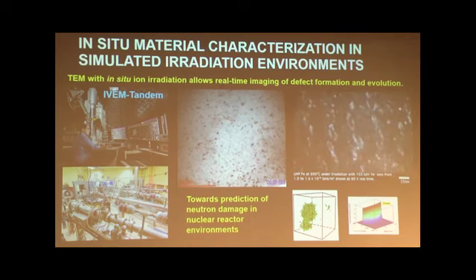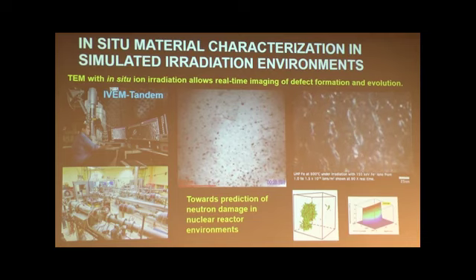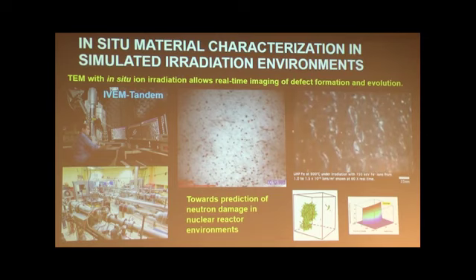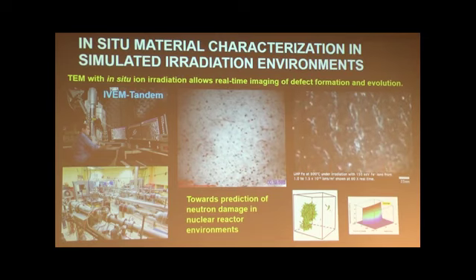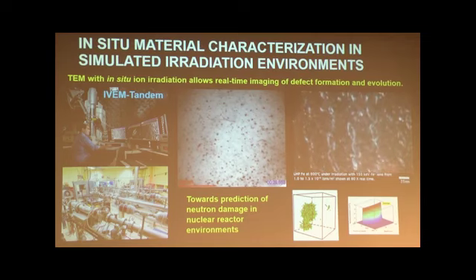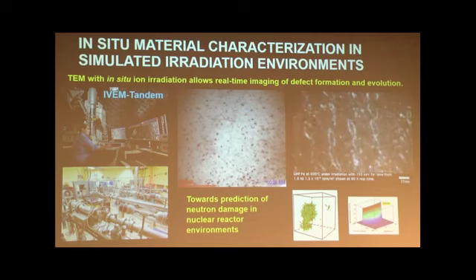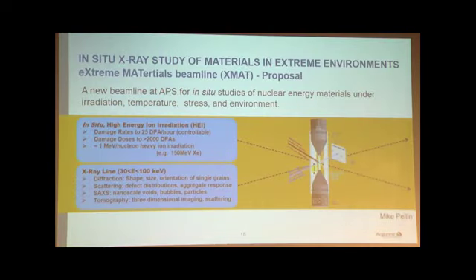Those little black dots are 1 or 2 nanometer dislocation loops. And this movie shows when the loops become larger, how they can even grow into different configurations and different sizes of defects. So it's important to have this kind of capability. So the question the community probably wants to think about is, should we also have a similar capability, adding an accelerator to do in situ radiation experiments with X-ray techniques? Argonne actually has a proposal called the Extreme Beamline XMAT proposal, to use both X-ray techniques and an ion radiation beam to damage the material at the same time and observe it.